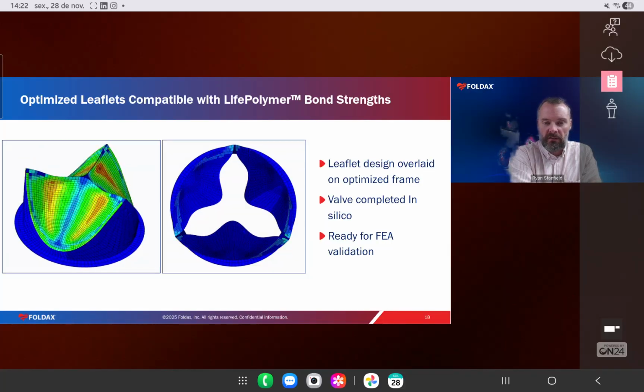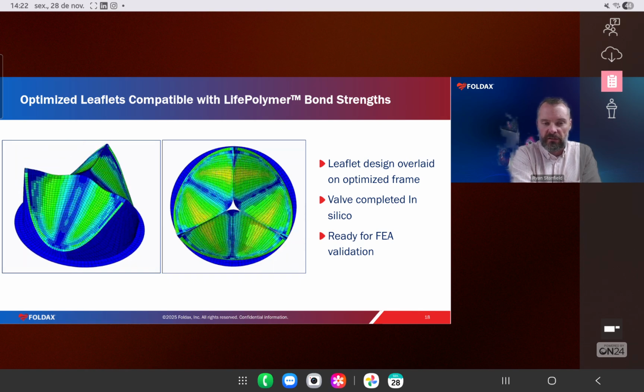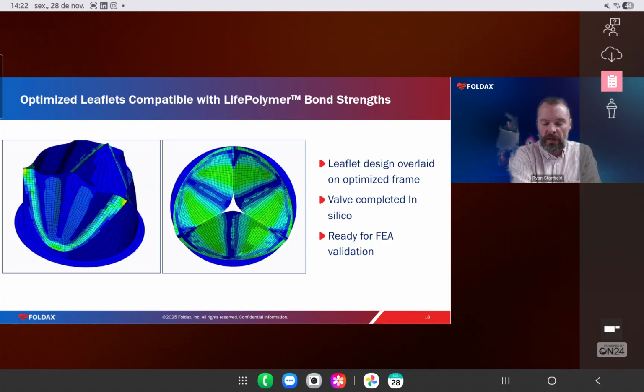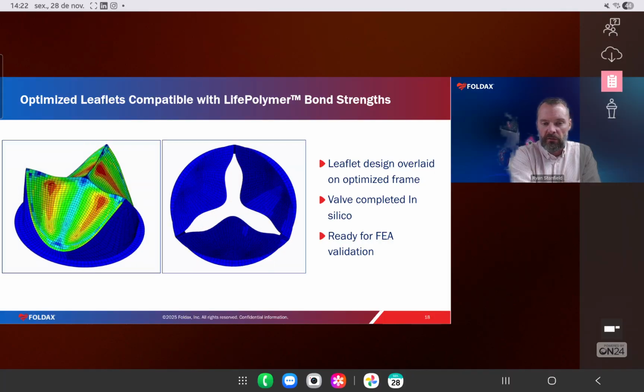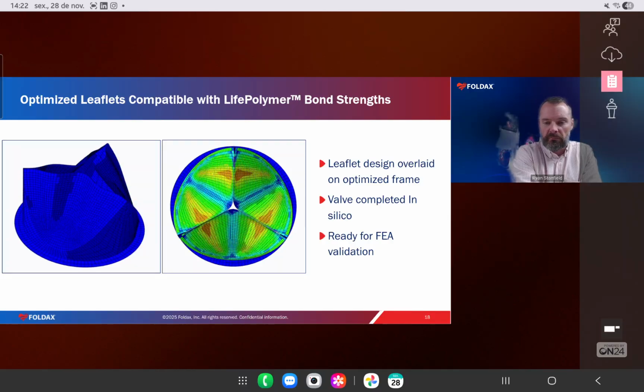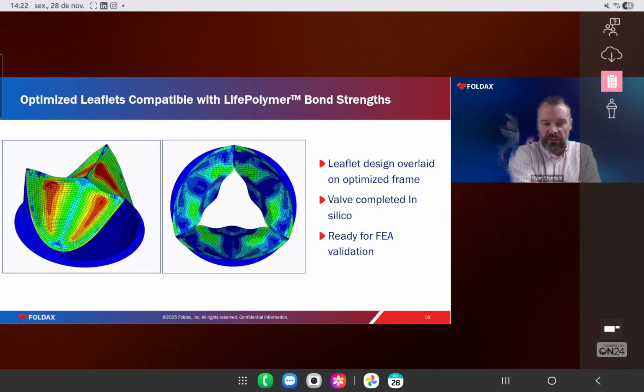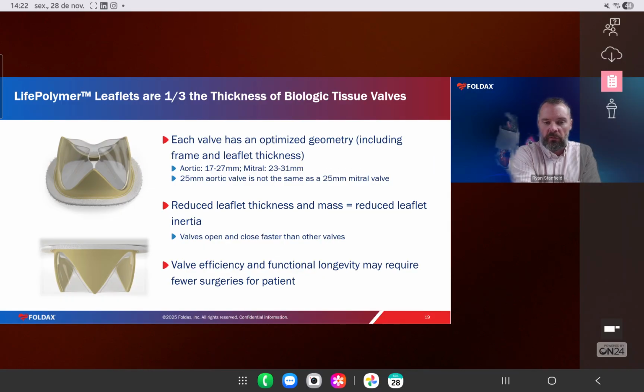And so we can apply that in our in silico models and complete our full design here, look at optimizing stresses and strains throughout the leaflets as well as in the frame, and look at flow patterns and how we'll do that and become ready for validating these models. With that designed and modeled, we can take that and optimize each valve for each environment. Right now, we make a series of aortic valves and a series of mitral valves. We make 6 sizes for aortics from 17 to 27 millimeter, and 5 sizes for mitral from 23 to 31. My point is that the 25 millimeter aortic valve is not the same as a 25 millimeter mitral valve. The frame and the leaflet thickness have all been optimized for each specific environment.